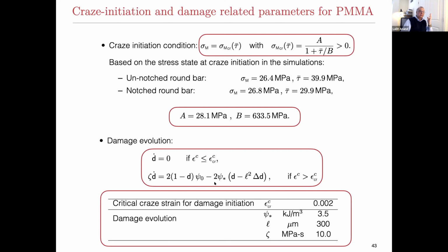And then you have, for the psi star, the length scale, and the viscous regularization parameter, you need some other numbers. This length scale, 300 microns, is perhaps not physically realistic, but if you go much smaller than that, then numerically it's very hard to do calculations. So there's some balance of psi star and L, which is needed to figure out how the damage is actually happening, to do it in a computationally tractable manner.